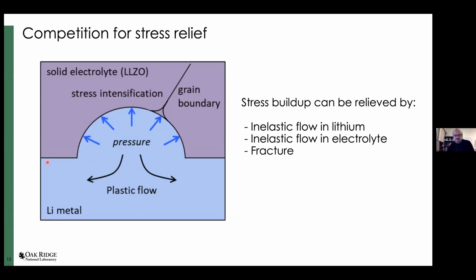It doesn't have to be lithium. We hear a lot about sodium batteries as well, but it's the interface with the metal, and you have plating into this void coming from the other side of the electrode of the cell stack, which creates the pressure. And this is where you start this war, this kind of competition on what to do with this stress buildup. So you cannot build it up infinitely.